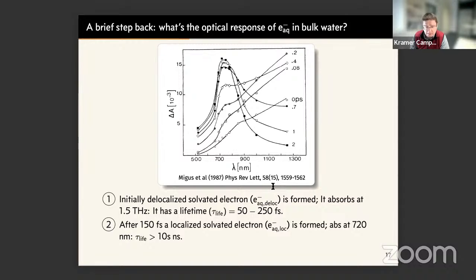So this is now just data from an older PRL by Migus and friends. And what you see here is the delay between the pump and probe pulse, right? So the pump pulse creates the solvated electron. You see at 0 picoseconds, at time 0, there is an absorption which is peaked far in the infrared. This is what I have described here in point number 1. And as you go forward in time, you lose intensity at long wavelengths. And by 700 femtoseconds or so in this case, you have this very clear spectral feature at about 720 nanometers.